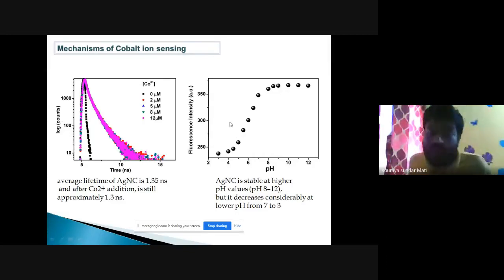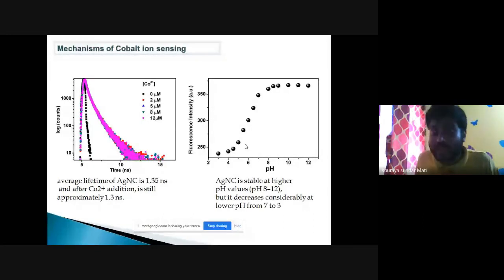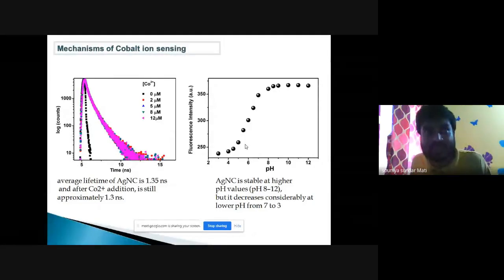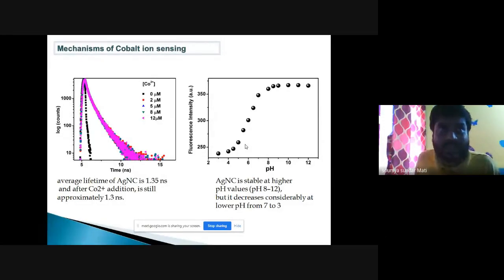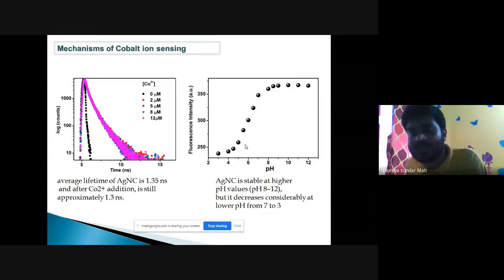This is due to the presence of H plus ion. The imine moiety of polyethylene imine polymer became protonated and it destabilized the nanocluster, and due to the destabilization the nanocluster became aggregated to form the nanoparticle and it loses its fluorescence intensity. And a similar observation is seen in case of cobalt 2 plus cation also. If we add cobalt 2 plus cation to polyethylene imine stabilized silver nanocluster, then the imine moiety forms a complex with cobalt 2 plus ion, and due to this strong complex formation, the imine moiety destabilizes the silver nanocluster, which becomes aggregated to form nanoparticle and loses its fluorescence intensity.